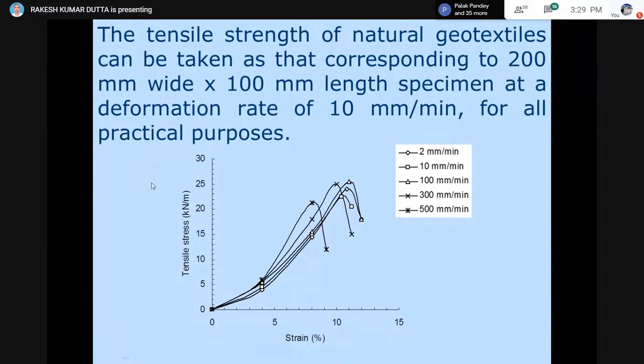And another study which was conducted during reporting of this data in the paper was what should be the size of the sample of the coir geotextile. So here a lot of sizes of the coir geotextile were tried, and one size was 20 centimeter by 10 centimeter. This was also tried. So the main conclusion of this study is that the value we obtain corresponding to the 20 centimeter by 10 centimeter specimen, the tensile strengths are very close to the actual one.